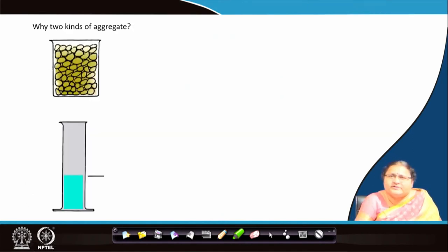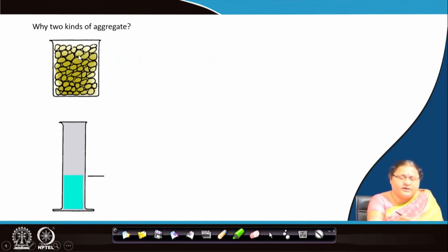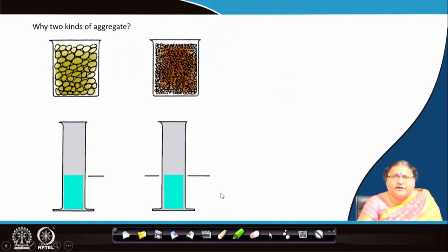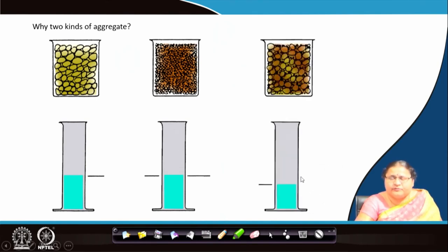Now, why 2 kinds of aggregates? You see in this jar with a specific volume, you can actually pour this amount of water into it. It will move through the spaces and will get accommodated. If we look into the fine aggregate and the same amount of water, the same amount of water will go into it. But if we mix the 2, the fine aggregate and the coarse aggregate, and then add the water, you will require less amount of water because the inter particle space is reduced.